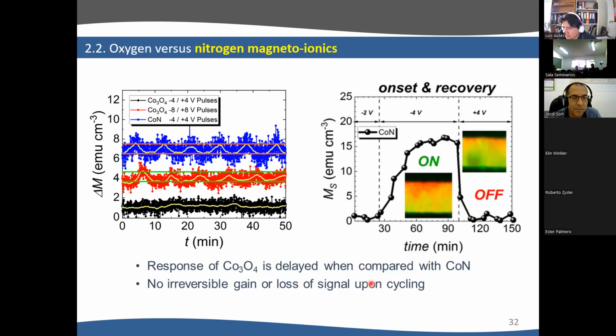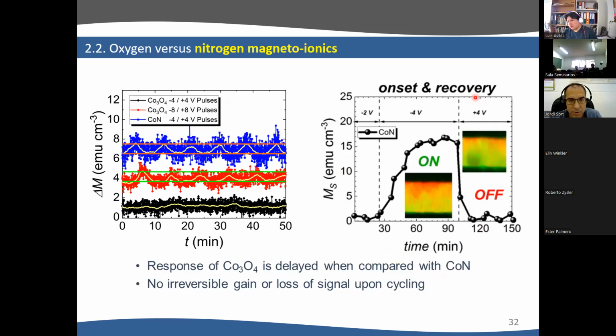For the two systems, cobalt oxide and cobalt nitride, we have good cyclability. Actually, for cobalt nitride, it's enough to apply -4 volts, so we are decreasing the voltage. And it works very well. And then what we want now is to further decrease the time. All I've shown here, even if nitrogen works faster than oxygen, is that you need something like half an hour, like 25 minutes, to reach this steady state equilibrium. But we want to speed up the process.